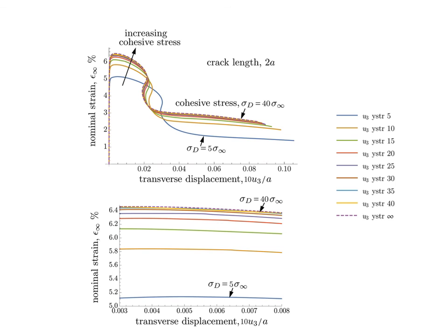and then there is a snap through that is impossible to follow in practice. Also, this leads to a risk that has to be considered, that there is some imperfection or somewhat unwanted displacement that will make the state jump from, let's say, straining of 3 or 4 to the bunch of curves, which also means that the load doesn't reach load of fracture. If you want to do a testing and fracture load is at 5 and 6, you may never end up there. You may have buckling first, and then you get some spooky results. The curve at the bottom is just a magnification of the top part of the graph.